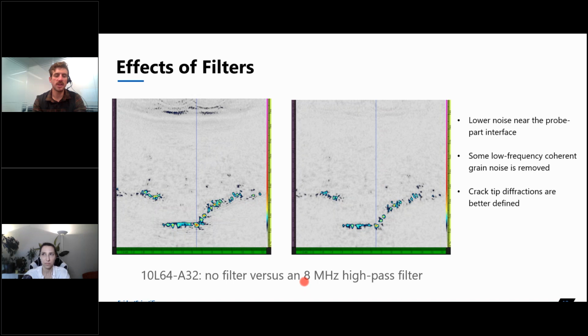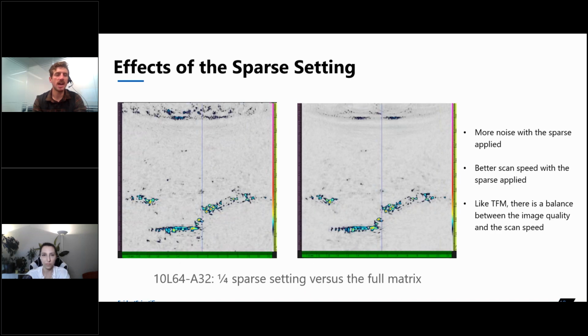And the same idea with the sparse setting, that when we are using the sparse setting, some of that coherent noise at the top of our part comes back, but this is still a very usable image, and we can still see quite a lot of detail in our actual defect. So the sparse, like I said, can very easily be used to increase productivity when it's necessary.